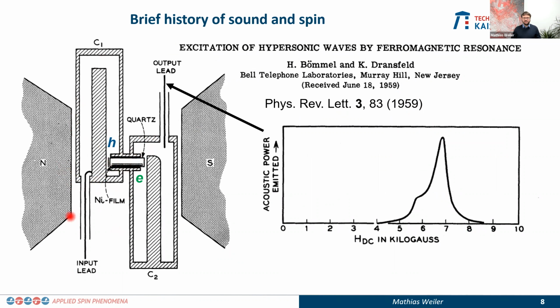And what they did is they used this input lead here and excited the microwave in this first cavity. One excites the ferromagnetic resonance of the nickel film, and because of the magnetoelastic coupling, it launches a sound wave. And because the quartz is piezoelectric, that leads to an electric field on the other side of the quartz, and that then couples to the second cavity, because here it is placed in an antinode of the electric field, whereas on the left-hand side, it's placed in an antinode of the magnetic field.